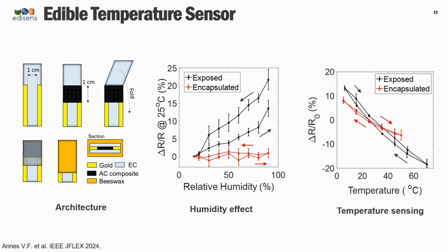However, you can encapsulate this material. As you can see here, we can encapsulate the material with edible material as well, which is mainly cellulose and wax, and edible gold foil to create contacts. When you encapsulate it, your material becomes virtually insensitive to humidity, because there is wax, and then you can use it again for temperature sensing. We have tried this and found a small deviation from the exposed material, but we have pretty good sensitivity for temperature sensing. So we can create a thermistor out of this.